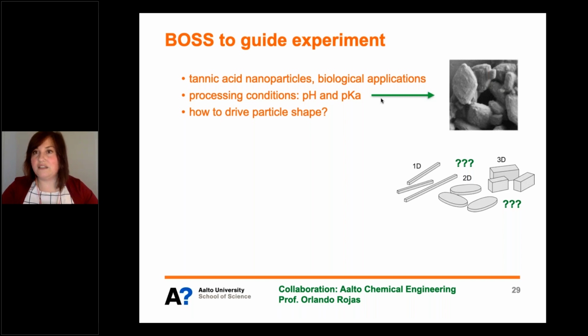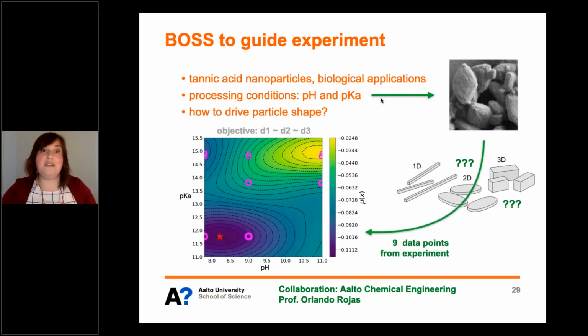So maybe one where D1, D2, and D3 are somehow similar. This objective function was then fitted with experimental data in the space of pKa and pH. And this is the kind of map we obtained. The global minimum in the bottom left is the darkest area. This is where everything should be 3D particles. And the bright yellow bit is where everything should be 1D particles. And we found that if we follow the field lines of this map, we're going from 1D to a 2D region to a 3D region. So this was our best estimate of what their particles would do.